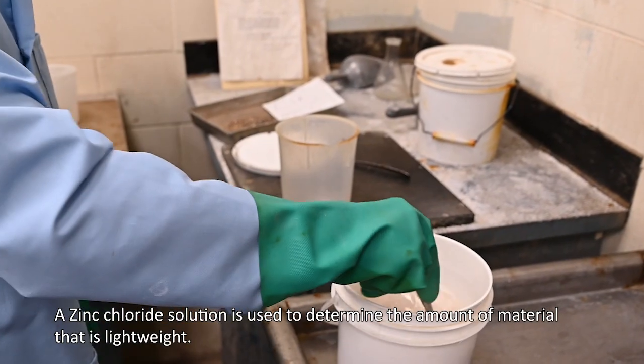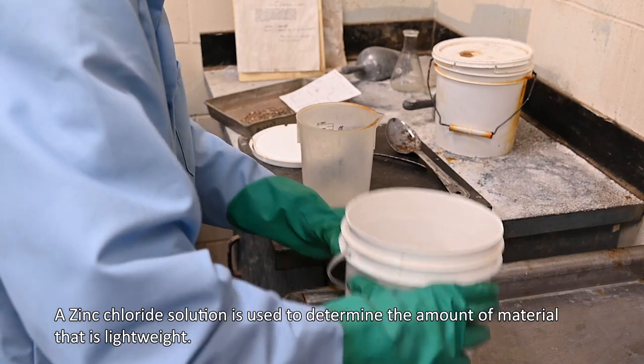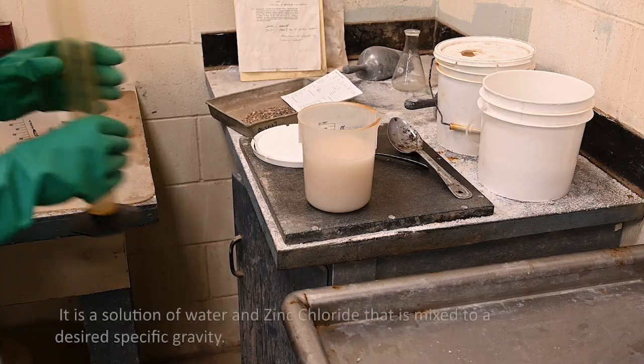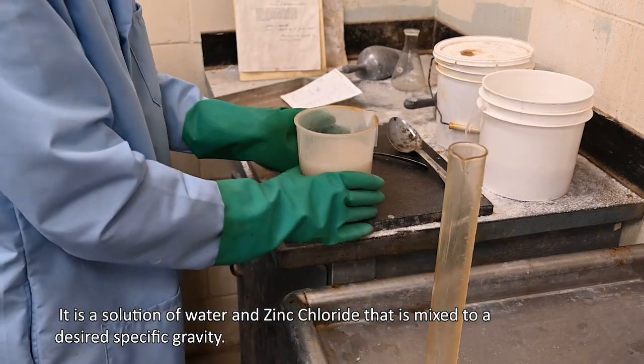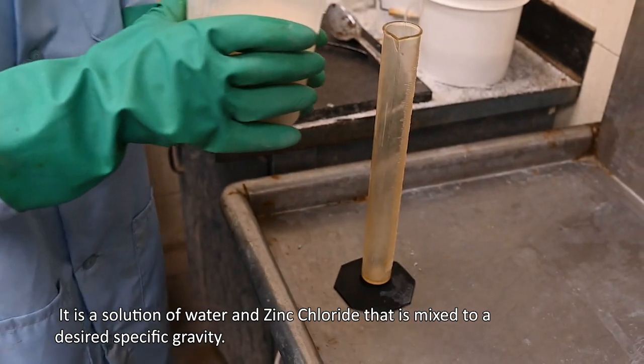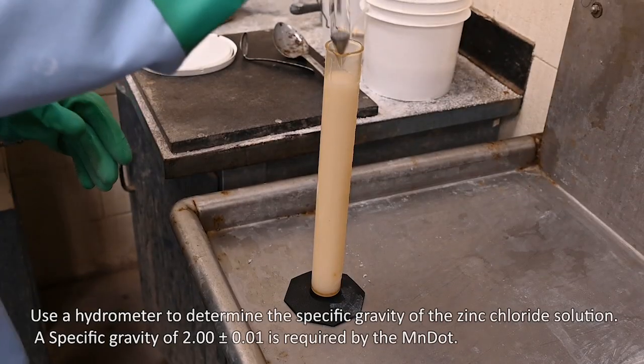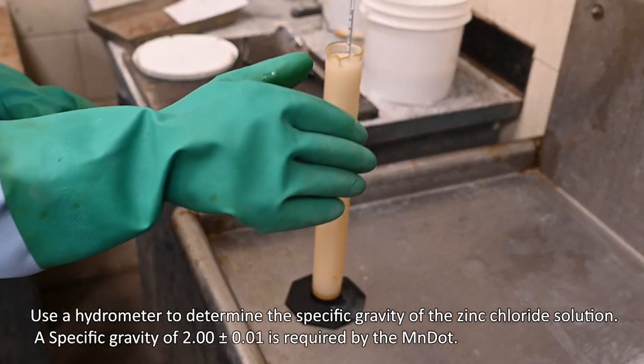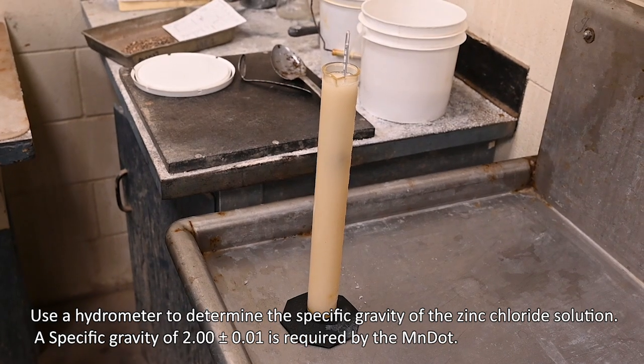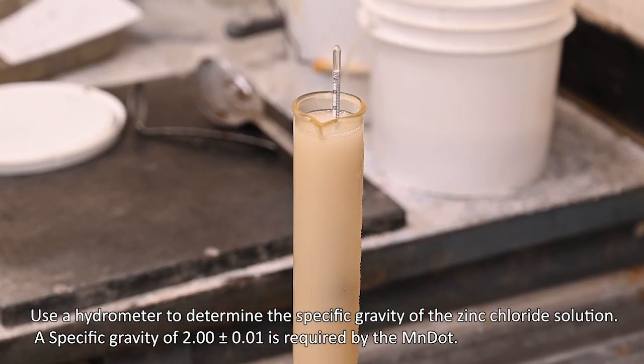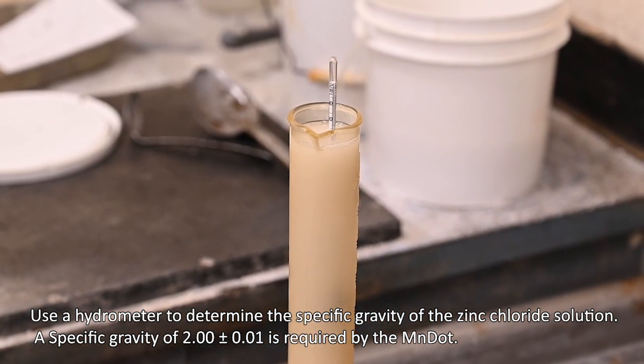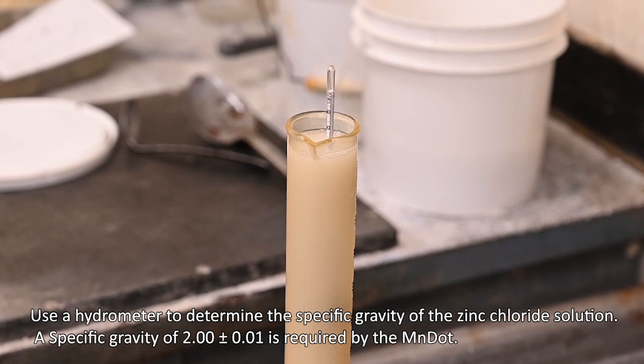A zinc chloride solution is used to determine the amount of material that is lightweight. It is a solution of water and zinc chloride that is mixed to a desired specific gravity. Use a hydrometer to determine the specific gravity of the zinc chloride solution. A specific gravity of 2.00 plus or minus 0.01 is required by MnDOT.